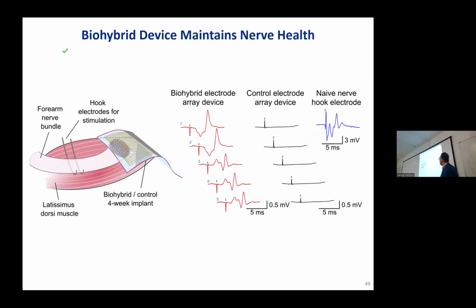So here, what you see is recordings from different electrodes that are placed on the nerve. So the nerve is severed, you present the array, you stimulate the nerve here, and then you measure activity here, different electrodes. These are data from electrodes without muscle that are placed on the nerve. And what you see is just a stimulation artifact and no further signal. And the reason for this is that this part of the nerve now is dead because after injury, the axons have died off. So you can stimulate all you want here, but there is no conduction of the signal.